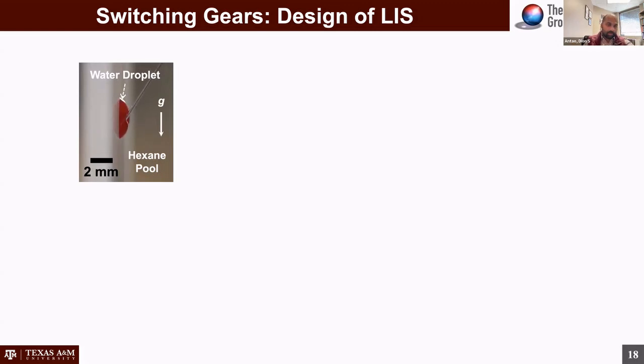We put this droplet near the quartz surface, and the water droplet displaces the hexane from the surface, which is somewhat counterintuitive. Hexane has a lower surface energy or surface tension than water. You would likely predict it to want to stick to silica and reduce the silica surface energy further. But water seems to have an affinity for the silica surface.